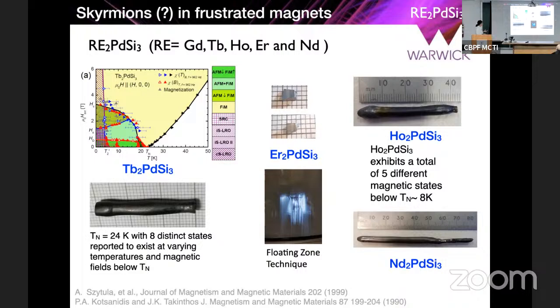For example, terbium, palladium, silicon shows about 8 distinct magnetic states, very different to each other, all listed here, which exist below the Néel transition of 24 Kelvin, okay? And all of these are very similar. But it was proposed that maybe some of these could also be hosts for skyrmions, especially the holmium or the erbium. So that's being studied. So the crystal sizes that you can obtain of these intermetallics are very large compared to those crystals that I showed you earlier of those other skyrmion materials obtained by chemical vapor transport.